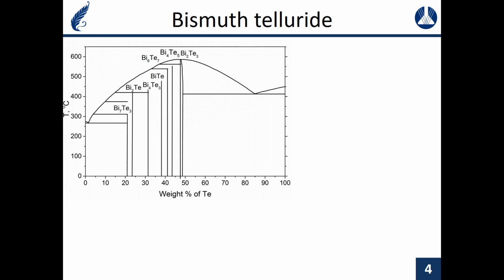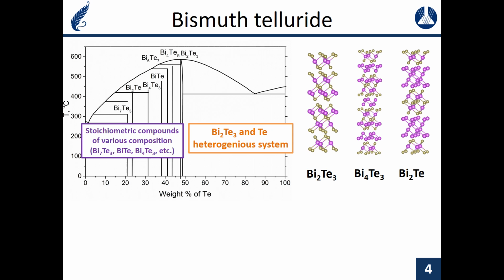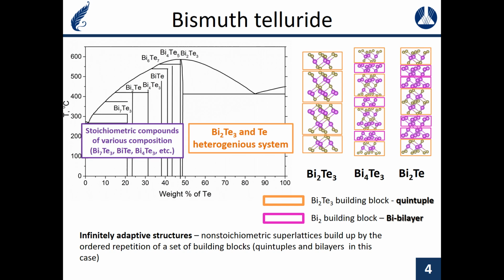According to the phase diagram of bismuth-tellurium binary system, heterogeneous system is formed at high tellurium content, whereas high bismuth content favors formation of variety of stoichiometric compounds like Bi2Te3, Bi4Te3, Bi2Te, and etc. The composition of these compounds can be described as a combination of two types of building blocks, a 5-layered Bi2Te3 quintuple and a 2-layered bismuth bilayer. In literature, structures formed by combination of these two types of building blocks are designated as infinitely adaptive structures. The infinitely adaptive series is not limited to stoichiometric compounds. In fact, any composition between the two lines of the phase diagram is possible.